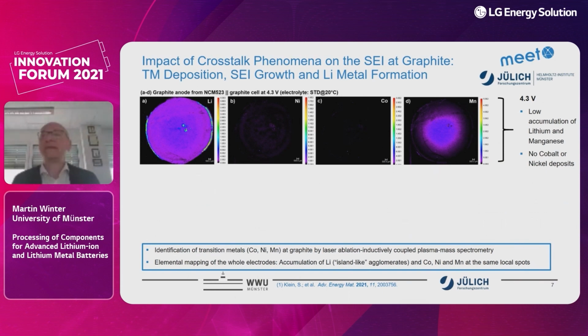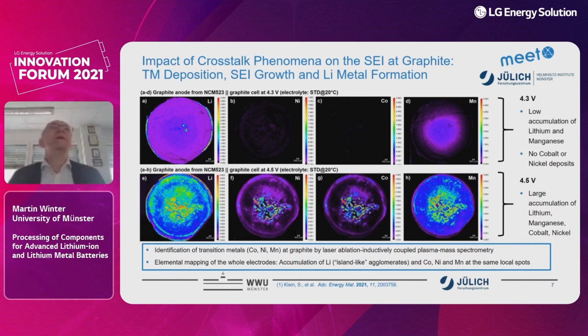If we look at this with laser ablation inductively coupled plasma mass spectrometry, which allows us to look at various elements that can be deposited on the surface of a graphite anode, lithium, nickel, cobalt, and manganese, we see that at 4.3 volt we have a low accumulation of lithium and manganese, and no cobalt or nickel deposits could really be found, very little nickel maybe. But at 4.5 volt, we see that all of these elements are present on the surface: lithium, nickel, cobalt, and manganese, which tells us that something has happened at 4.5 volt.